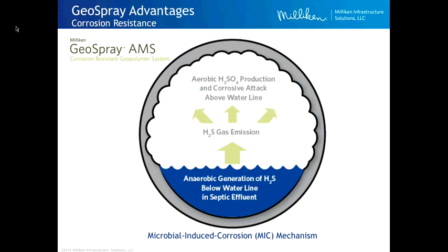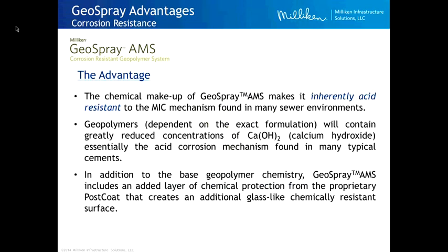So most of you deal with sanitary sewers, and we know how hydrogen sulfide gas gets formed through the anaerobic breakdown of the material and the effluent. That gas collects on the pipe wall, and then the bacteria on the pipe wall lining break that down further. That basically oxidizes the hydrogen sulfide gas and forms sulfuric acid, and that's what attacks the Portland cement. So during the generation of Portland cement, you get calcium hydroxide molecules. They react with the sulfuric acid and form gypsum, which is water soluble, and that's what dissolves the concrete. That's why concrete just dissolves over time. Our material, we do not have calcium hydroxide molecules, so we don't have the same chemical reaction that occurs.